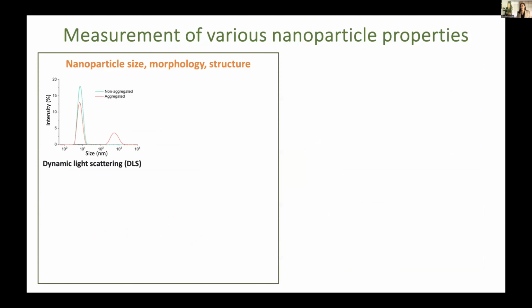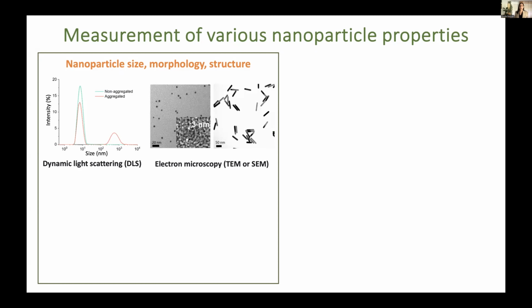For size, dynamic light scattering, DLS, is a very commonly used method. It not only measures the hydrodynamic diameter of nanoparticles in solution, but it can also show you if your particles are aggregated or not. And if you want to get more information on size and morphology, as well as for nanoparticles that are non-spherical, electron microscopy has been very advantageous, both TEM and SEM. And you can use the high resolution version of TEM to even start to see the lattice structures of very small nanoparticles like this carbon dot here.